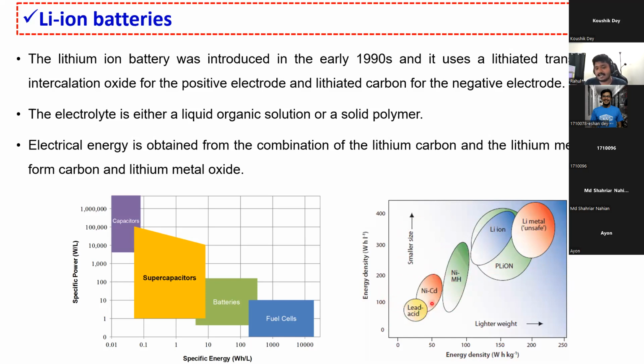Secondary batteries like lead acid, nickel cadmium, nickel metal hydride. You can see from this plot that lithium metal batteries have higher energy density. The reason is that we are using the lithium metal as such, so we can get the maximum capacity out of it. But the major problem with lithium metal is the dendrite issue. There is a hair-like growth, which is happening in this kind of batteries, which actually determines the performance of the battery. That's why people are going with the lithium-ion battery rather than lithium metal batteries.